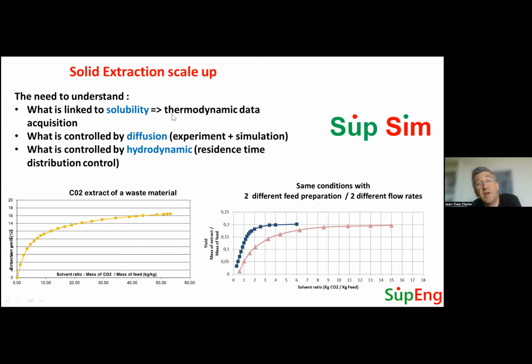And with some other methodology, like the one we use in chemical engineering, we can do some residence time analysis for the extractor to try to estimate what could be the remixing, because this is one of the challenges here. We want to go to very low residual content of the pollutants and of the plasticizers. So we have to optimize hydrodynamics, and the main limiting factor is diffusion. So we can again model this to understand everything, and with a couple of simulations and a couple of additional experiments, we could reduce the original curves that we obtained at lab scale to much more interesting conditions, when we reduce the amount of solvent by a factor of 10, going from 50 to almost 5.